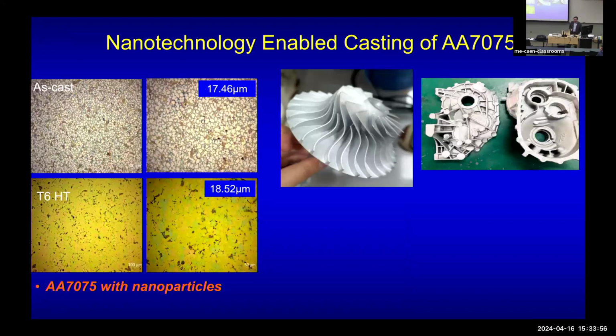And here is the first one, nanotechnology-enabled casting of 7075. 7075 is an aerospace alloy, the highest strength in the commercial domain for aluminum alloy. This is normally very difficult to manufacture. Generally speaking, the aerospace industry talks about the buy-to-fly ratio, right? So they talk about 10 to 1. It means you buy 10 kilos, you only use 1 kilo to go to the sky, right? 9 kilos is all machined off. So this is a really costly process.